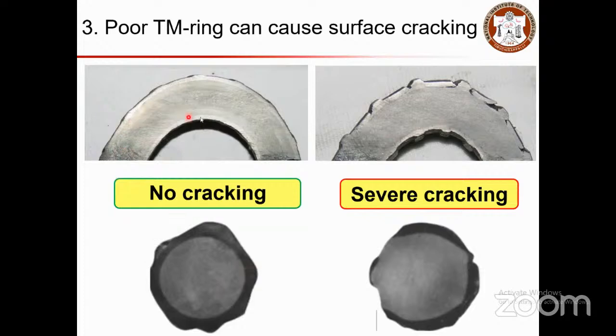When you bend a good cross sectional bar, you will not see any cracking on the surface. Whereas if the cross section is not good, that is if the TM ring is not uniform, and when you bend it, then you will be seeing a lot of severe cracks like this. So this is going to affect the durability performance of your structure when these bars are going to be used